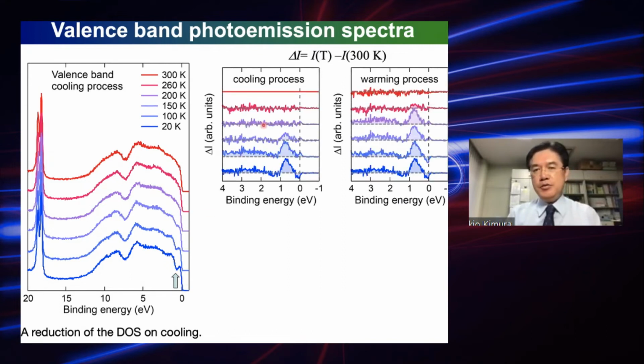And we took the difference between the spectrum at a certain temperature and the spectrum at 300 Kelvin. Then you see the dip corresponds to the negative peak in the difference spectrum. As you can see, the dip grows from 150 Kelvin down to 20 Kelvin. And you also see a positive peak here. This corresponds to the appearance of the sharp peak near the Fermi energy.